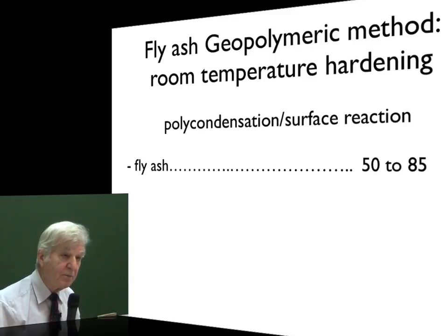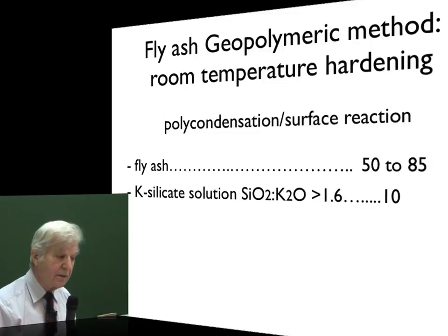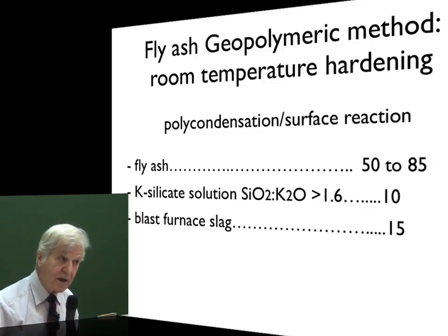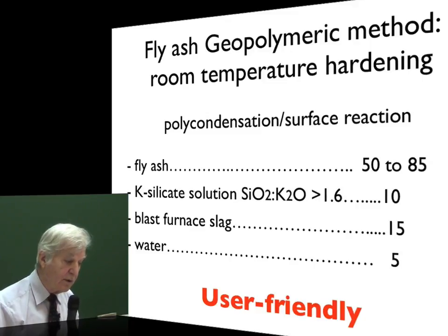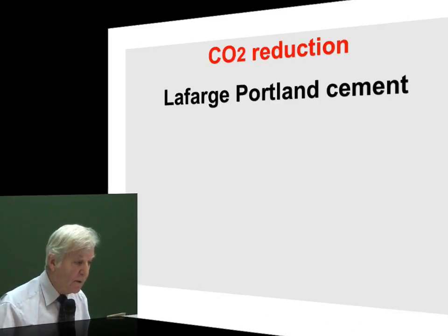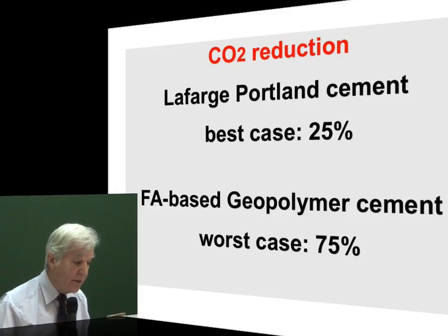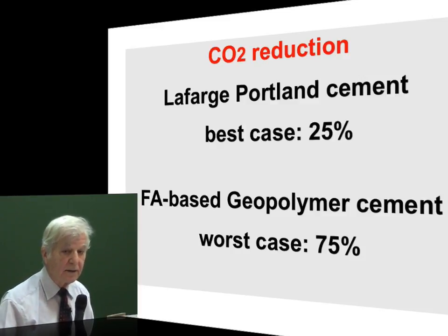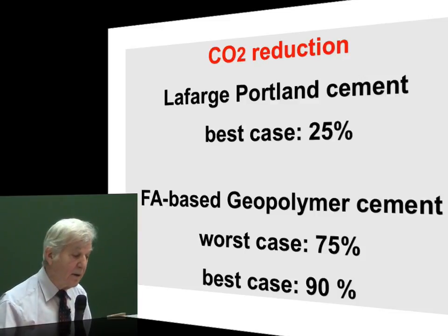We have 50 to 85% by weight of fly ash. We use a very, very weak potassium silicate solution. We use blast furnace slag as a chemical ingredient, activators, and water, and it is user friendly. And you see that we have practically a small amount of chemical ingredient that we have to purchase and to manufacture, and a high amount of fly ash, and it is user friendly, and it is a cement. So, if we compare with the best case for Lafarge, fly ash based geopolymer cement, worst case if we have to manufacture all the ingredients except fly ash, because I don't want to be trapped by this tale that we have to manufacture fly ash, which is nonsense. Best case, 90%.